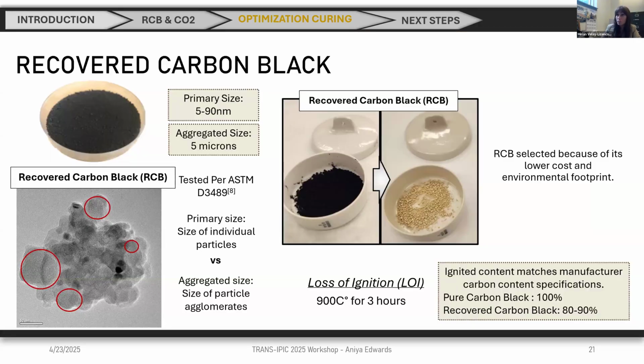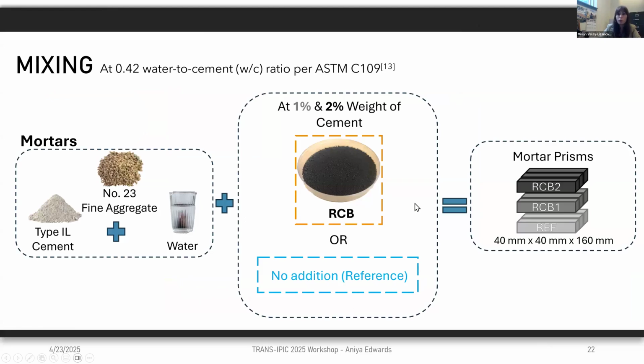So again, this is the recovered carbon black, which is not 100% pure, as you can imagine. That's the reason why it's called recovered. Well, the reason is because it comes from tires, but it has a little bit of impurity. And what we did is we made mortar mixtures at the beginning with no recovered carbon black, with 1%, and with 2%.